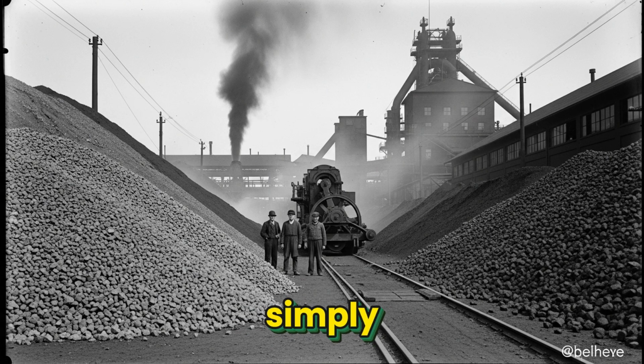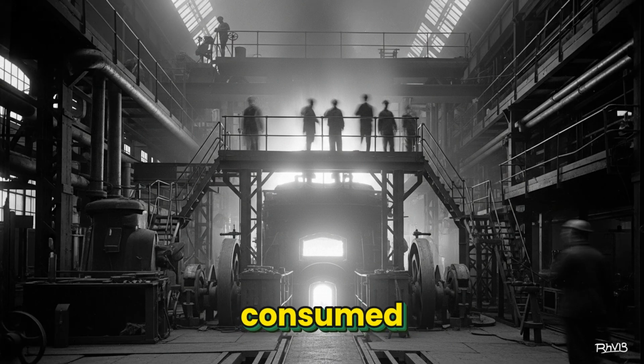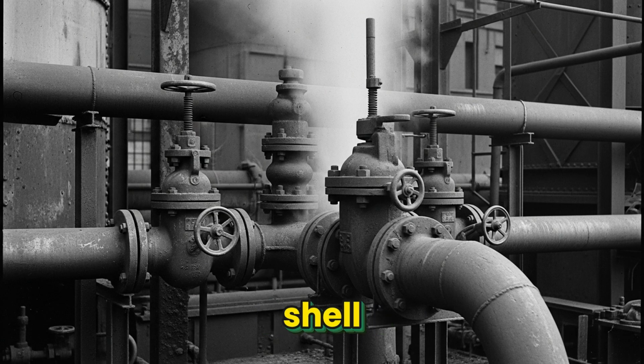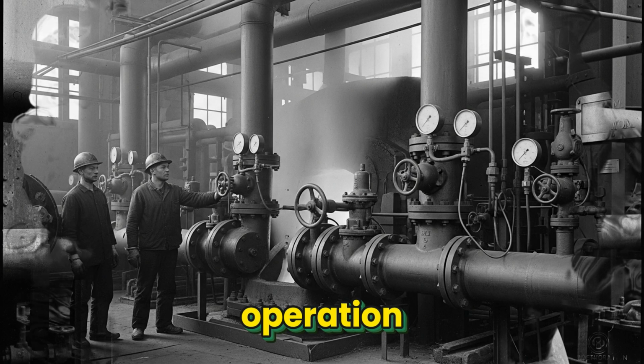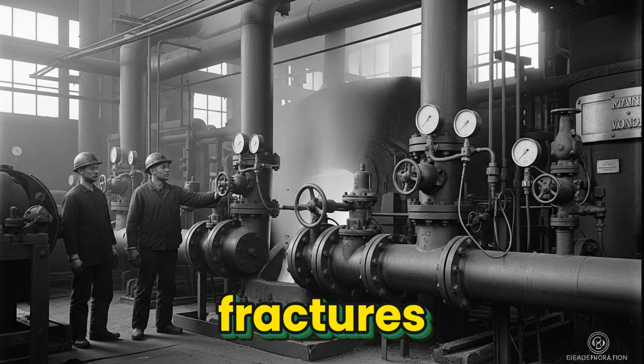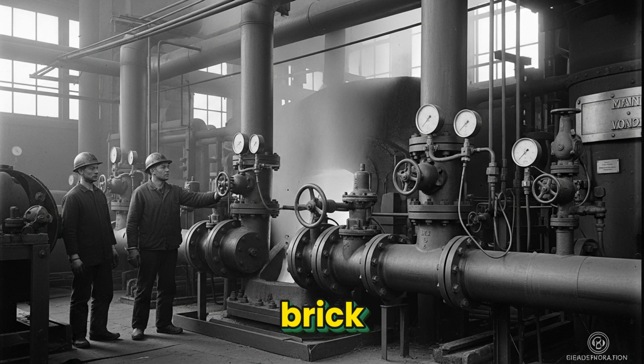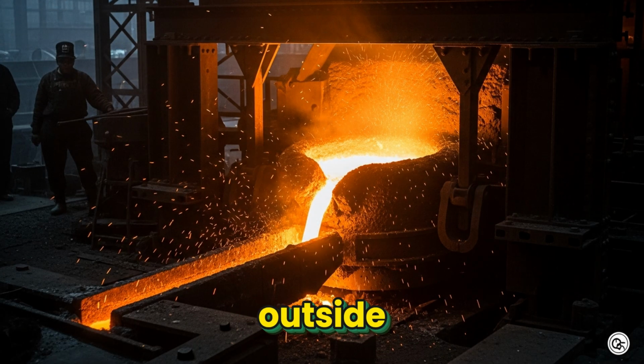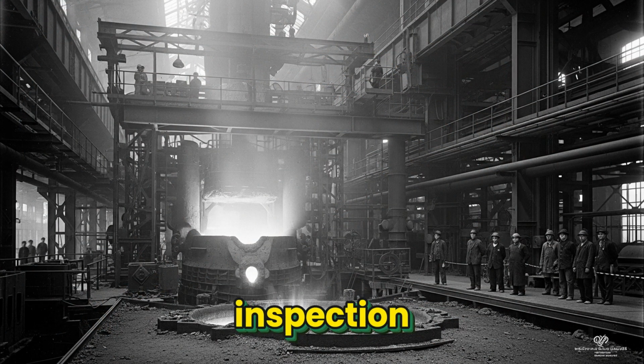Steel does not simply endure heat, it is slowly consumed by it. Every cycle of extreme temperature causes the furnace shell to expand and contract, and over months of continuous operation, that movement opens microscopic fractures inside the metal and brick. They are invisible from the outside. They grow in silence, behind layers of casing that no inspection reaches while the furnace remains active.